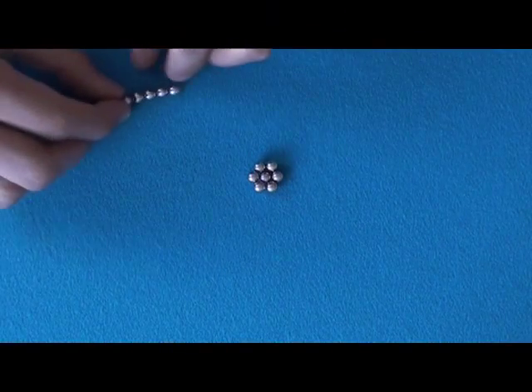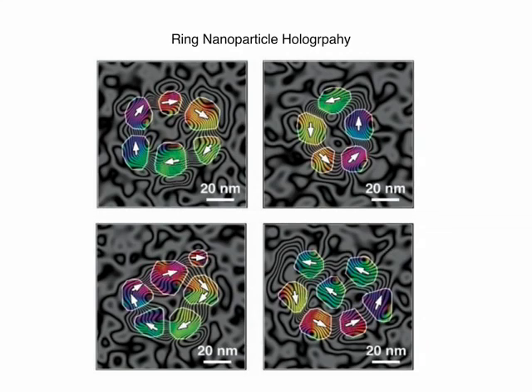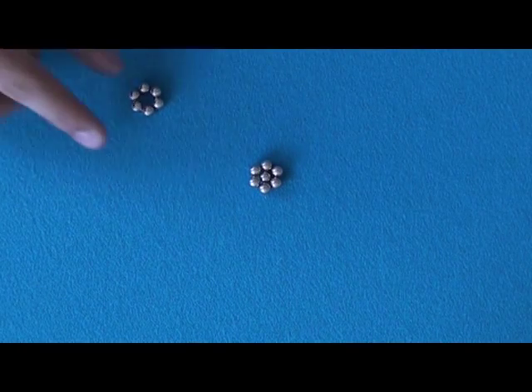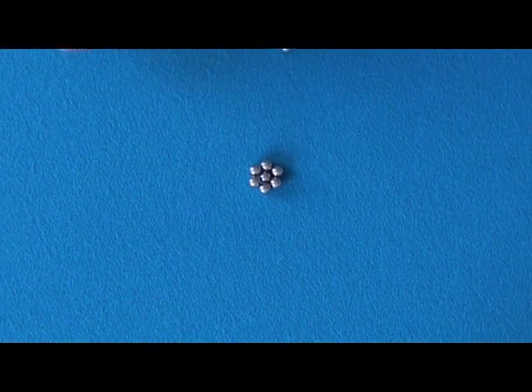However, if we take the same chain and make it into a ring, then its net magnetic moment is reduced to zero, and there is now no external magnetic field generated. We can illustrate this by using images from electron holography. These are cobalt nanoparticles arranged into rings — the magnetic flux is entirely contained within the ring, and there is very little external magnetic field. The lack of external magnetic field means that the ring of beads no longer causes the compass to rotate.